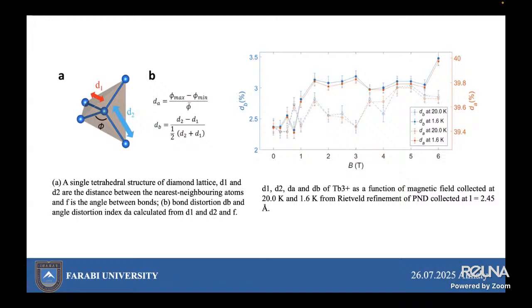In this picture, you see a single tetrahedral structure of the diamond lattice, where D1 and D2 are the distances between the nearest neighboring atoms, and phi is the angle between bonds. The bond distortion and the angle distortion indexes are calculated using D sub 2, D sub 1 and phi.